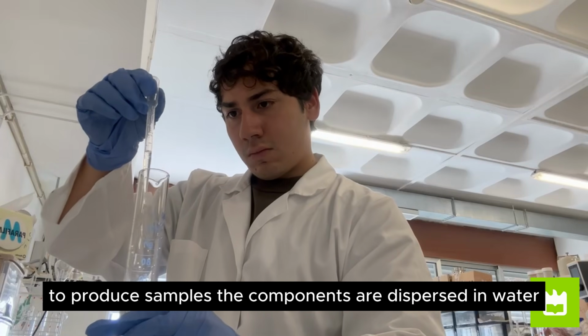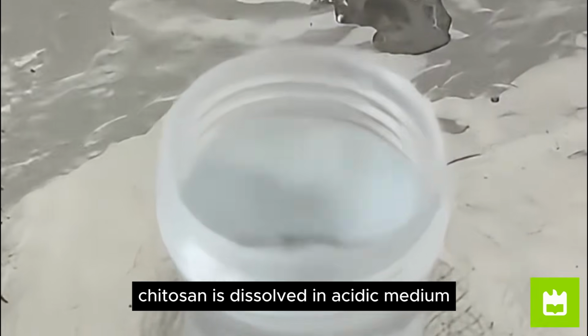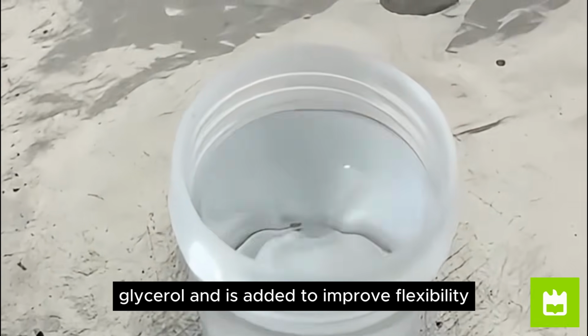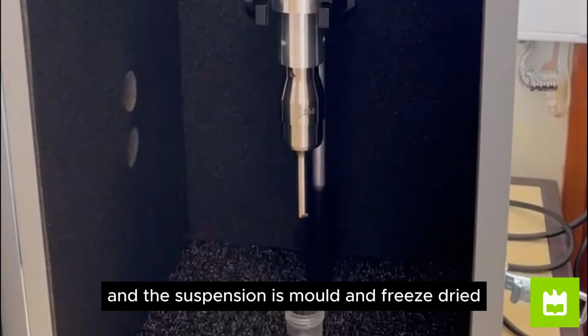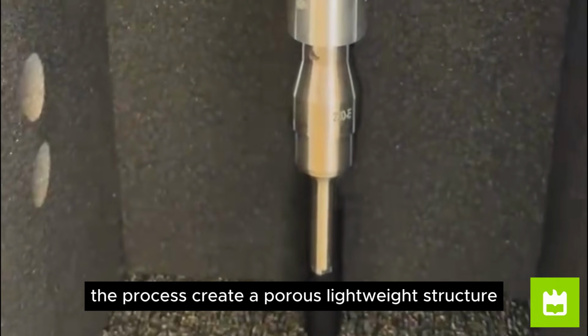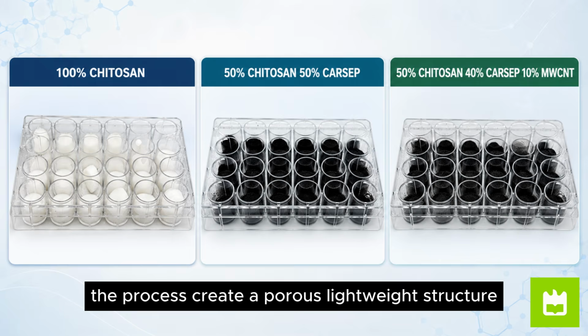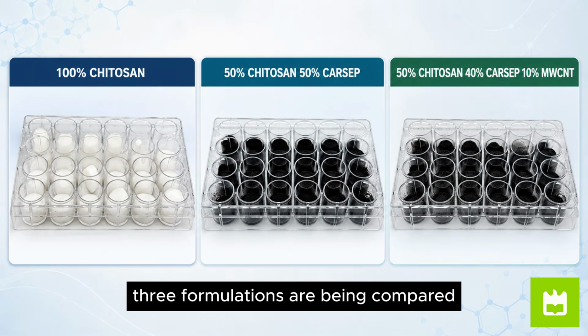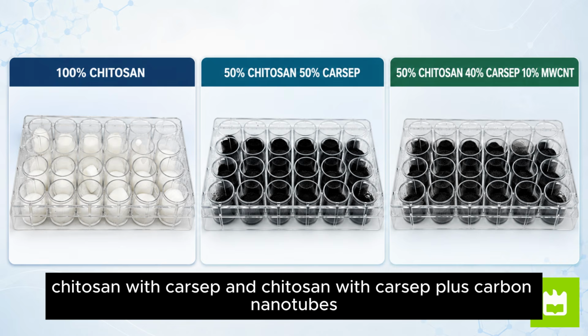To produce the samples, the components are dispersed in water. Chitosan is dissolved in acid medium, and glycerol is added to improve flexibility. The suspension is molded and freeze-dried. The process creates a porous, lightweight structure. Three formulations are being compared: pure chitosan, chitosan with CARSEP, and chitosan with CARSEP plus carbon nanotubes.